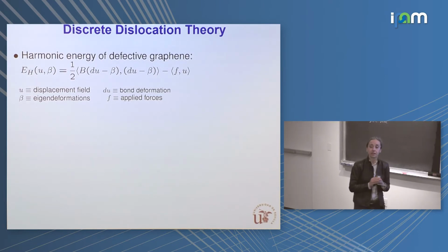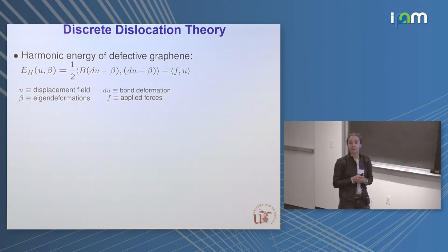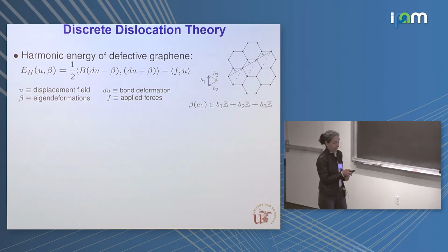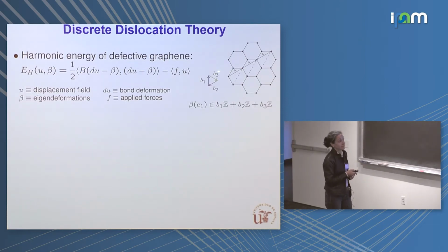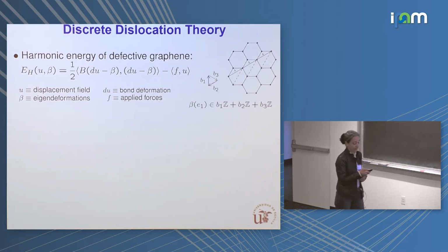Very simple equation, an equation that is going to allow us to really get defects in a very easy way. And the good thing is that those defects are stable, and you can identify them very easily. So these are the kind of slips that we introduce, slips along a zigzag chain of bonds, and we obtain this eigendeformation in terms of individual discrete slips in different interatomic bonds, as you see here.